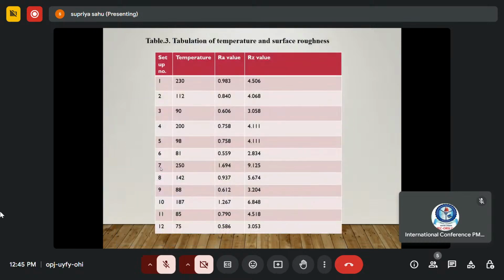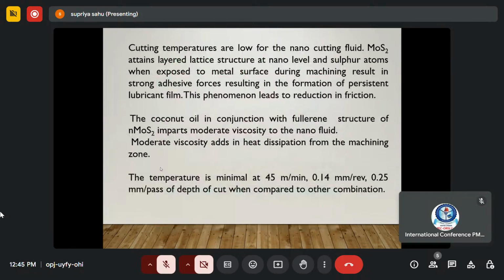This is the tabulation of temperature and surface roughness. After the machining, the temperature is measured, and these are the Ra and Rz values. So the cutting temperatures are low for the nano cutting fluid. MoS2 attains a layered lattice structure at the nano level, and sulfur atoms, when exposed to the metal surface during machining, result in strong adhesive forces resulting in formation of a persistent lubricant film. So this phenomenon leads to reduction in friction.